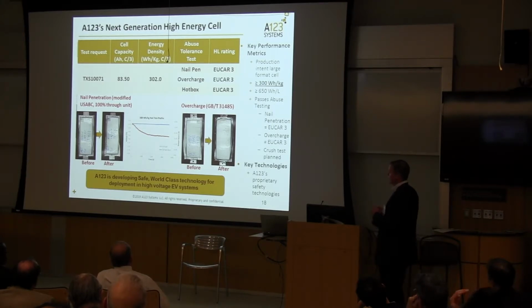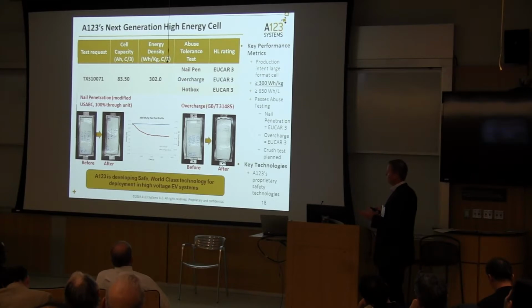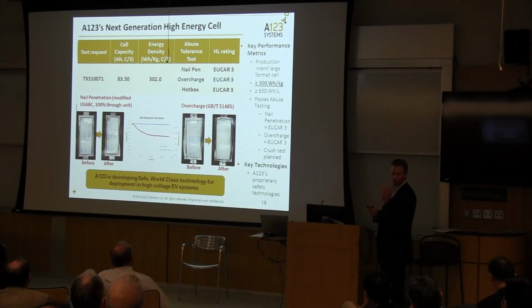So we wanted to take the same approach but up the energy density. The way that we did that was by incorporating silicon in it, so we can consistently be over 300 watt hours per kilogram. With silicon, we incorporate these doping and these coating efforts into these particular cells as well. And you could see these are 84 amp hour cells, again, made on production intent equipment, and you could see that it's a very benign result. Really, this EUCAR 3 rating means that essentially there is enough heat that's generated internally so that some electrolyte actually evaporates out of the cell, but there's really no flame or any sort of reaction.